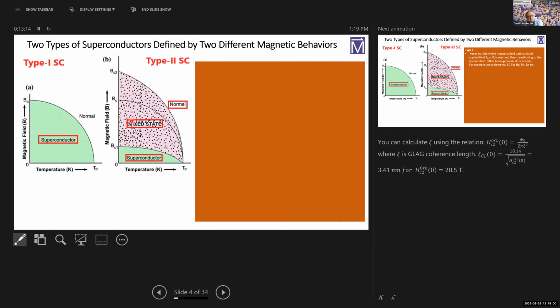And then complete loss of superconductivity at a higher field, BC2, right here. BC here becomes now a thermodynamic parameter where the energy of the superconducting state is a half BC squared over 2 mu 0 per unit volume. But the physical changes occur at the upper critical field, BC2, and the lower critical field, BC1.